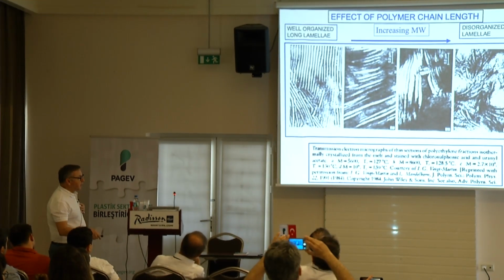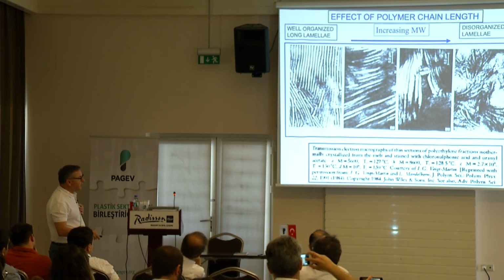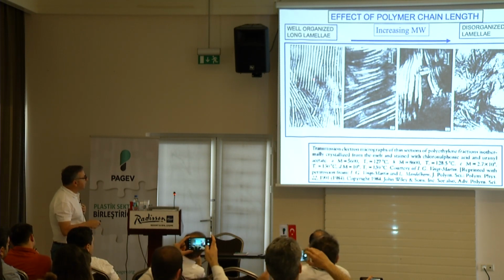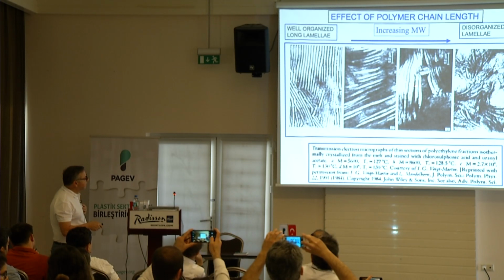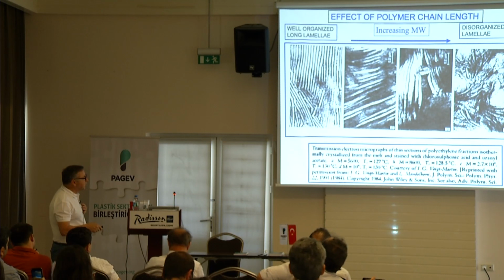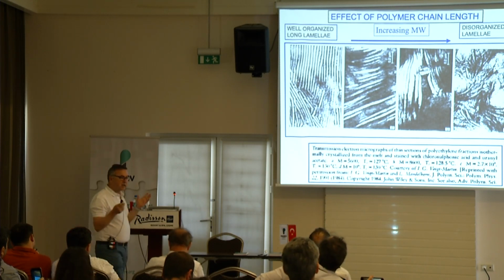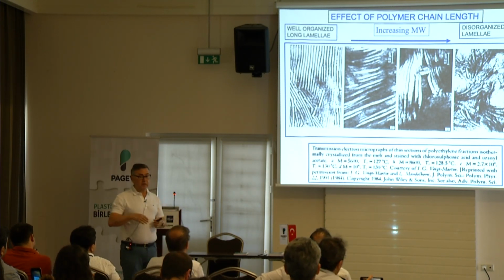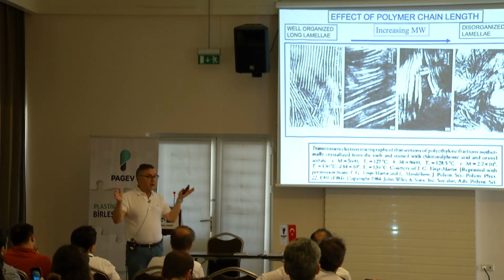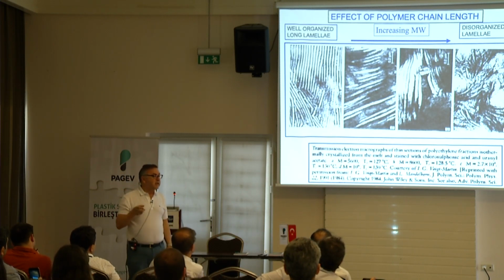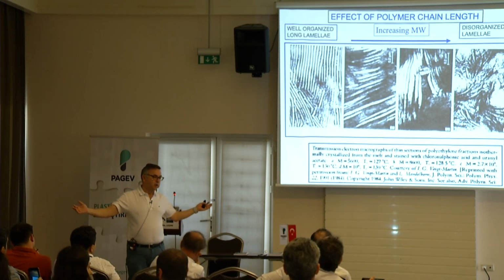Molecular weight chain length. Remember the molecular weight distribution that I showed you on the graph here, that if you make the material fractionated, make it really long chain molecules, this lamellar structure gets less and less perfect. Look at that. There's high molecular weight, long chain molecules, they don't do very well in getting these perfections. So when you go to really high molecular weights, even though you have the same repeat unit, crystallizability or crystal structure integrity decreases for the long chain molecule.